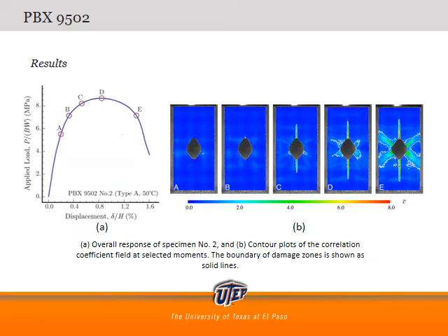In the experiment, the load was applied and increased, and the displacement of the specimen was observed and graphed in figure A. As you can see, points A, B, C, D, and E all correlate to the contour plots in figure B. The contour plots show the increase of the crack formation that occurs as the load is applied. You can see in point B that the crack begins to form at the top and the bottom of the cavity, and begins to increase in part C. Once the load reaches point D, widespread shear damage begins to occur and cause detrimental damage to the test specimen.